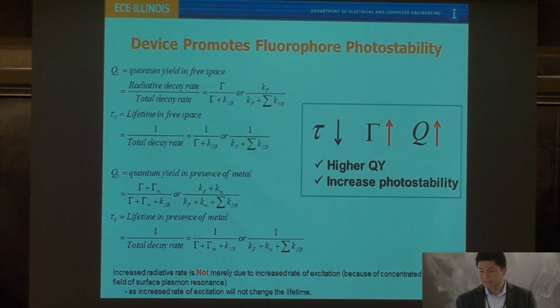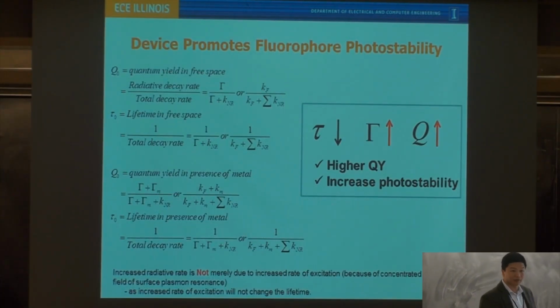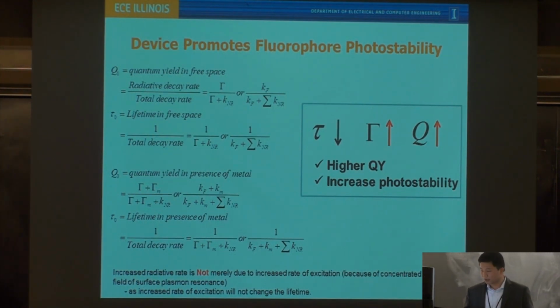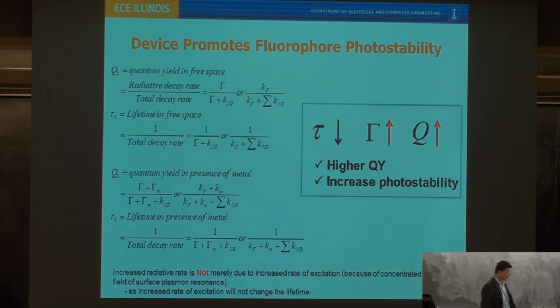So how much does the lifetime go down, and how much does the quantum yield go up? Well, I didn't bring the table here, but it actually varies from molecule to molecule. It's really molecule dependent. For quantum efficiency, the best case we have is about 4 to 5 times enhancement. For some high quantum efficiency fluorescent molecules like Rhodamine 6G, there will only be very little change.